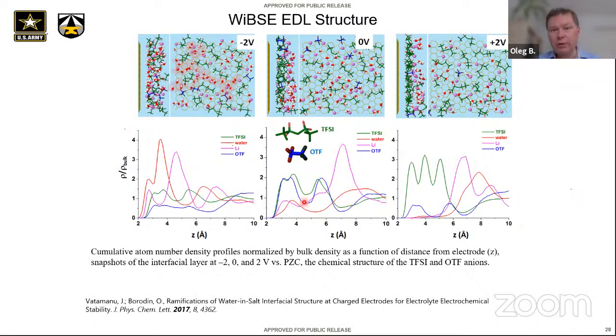So the majority of lithium with water wants to go here. That would be the outer Helmholtz layer, close to the diffuse double layer. There is very good news happening at the positive electrode. Once we put a positive potential, anions come in, and water gets completely pushed out. There is no water in the inner Helmholtz layer. There is also another interesting point occurring here: TFSI comes in, while triflate actually gets lower.